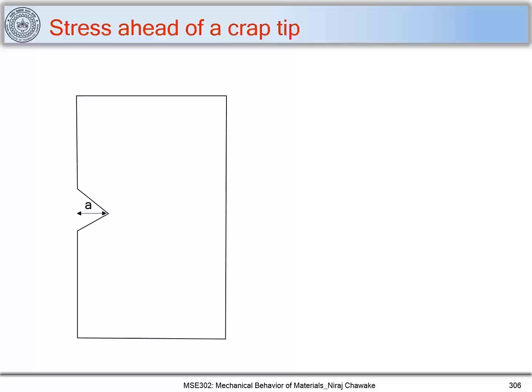So for that, let's consider this sample which has a surface crack of length a, and let's mark a coordinate axis like r here ahead of the crack tip, and sigma yy, that is the stress along the y direction. And let's say if we don't have a plastic zone ahead of the crack tip, or let's say the material is elastic or a very brittle material, you will see the stress field ahead of the crack tip varying in this fashion, where you reach a very high value of stress just ahead of the crack tip. We have seen this in an earlier part.